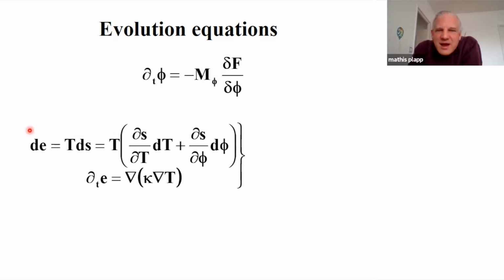And for this, I need to use, on the one hand, that I have a conservation law for the internal energy. So if the local energy changes, it's because I have a heat current. So kappa here is the heat conductivity. Nabla T is the temperature gradient. So this is Fourier's law of heat conduction. This is a divergence. So this is nothing but a heat conservation equation.